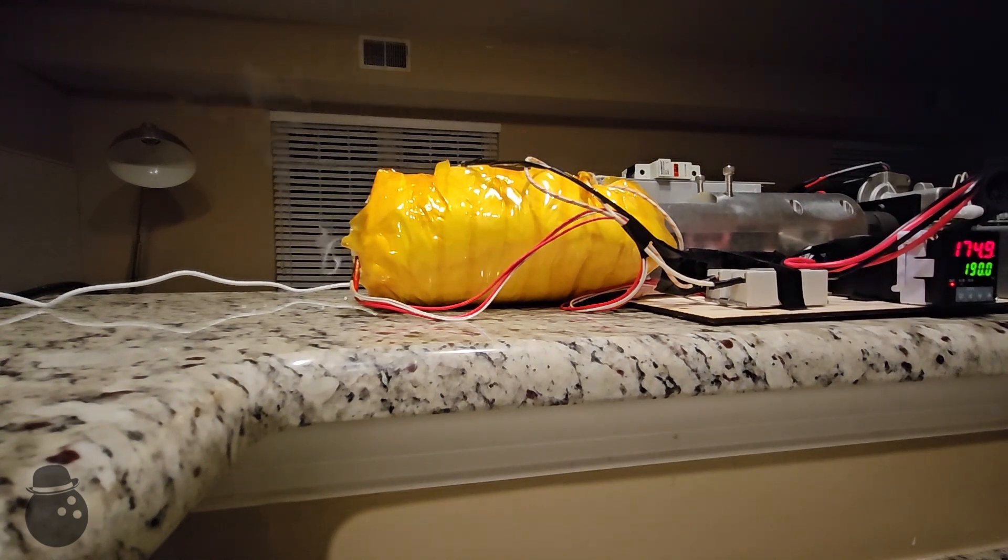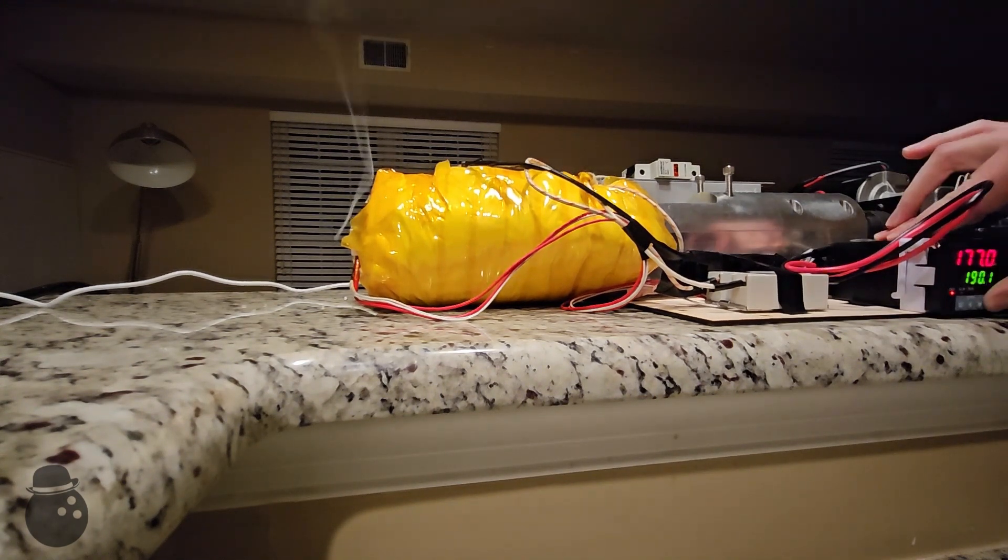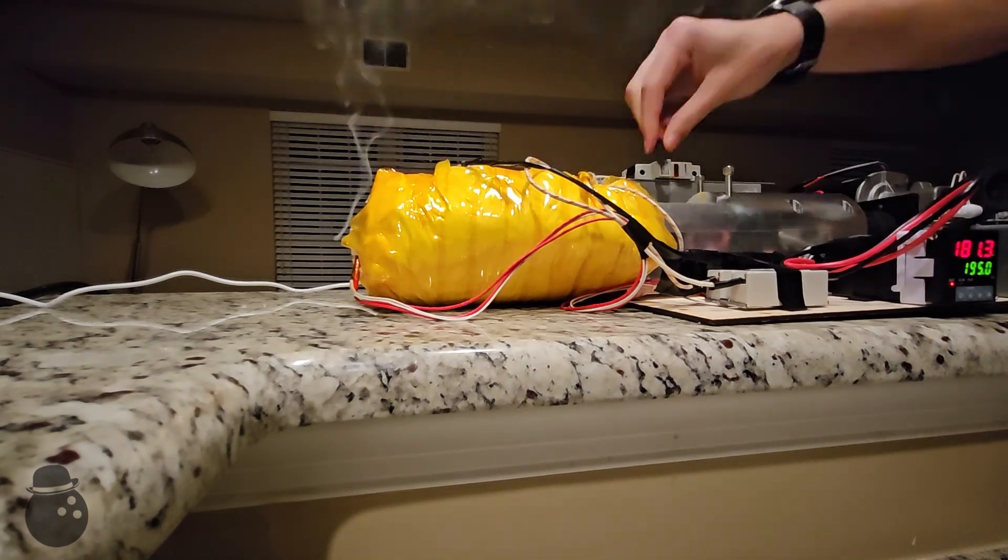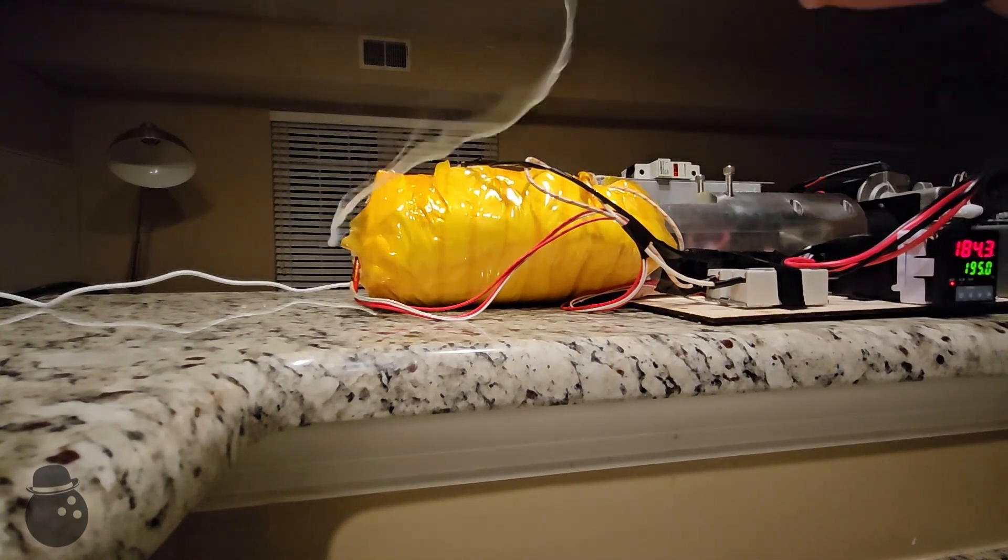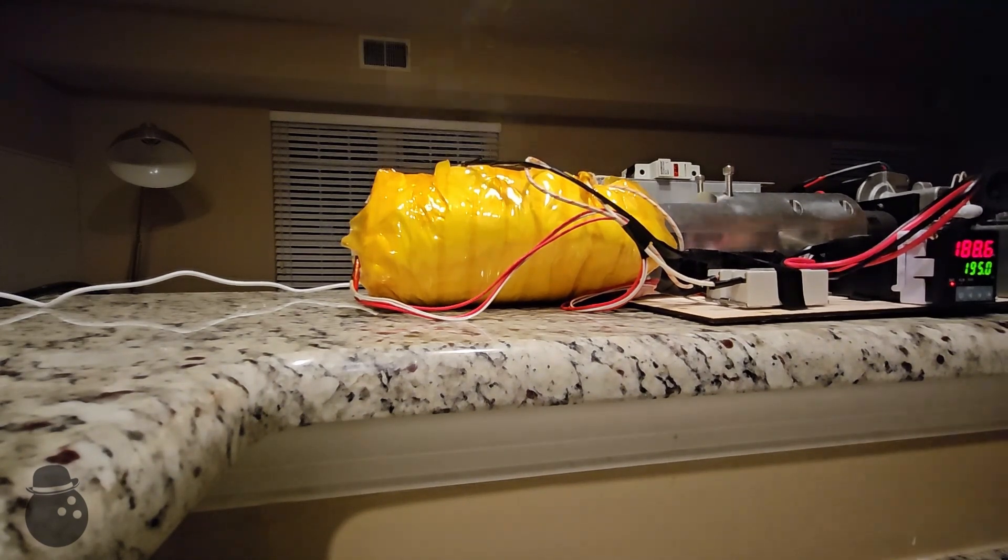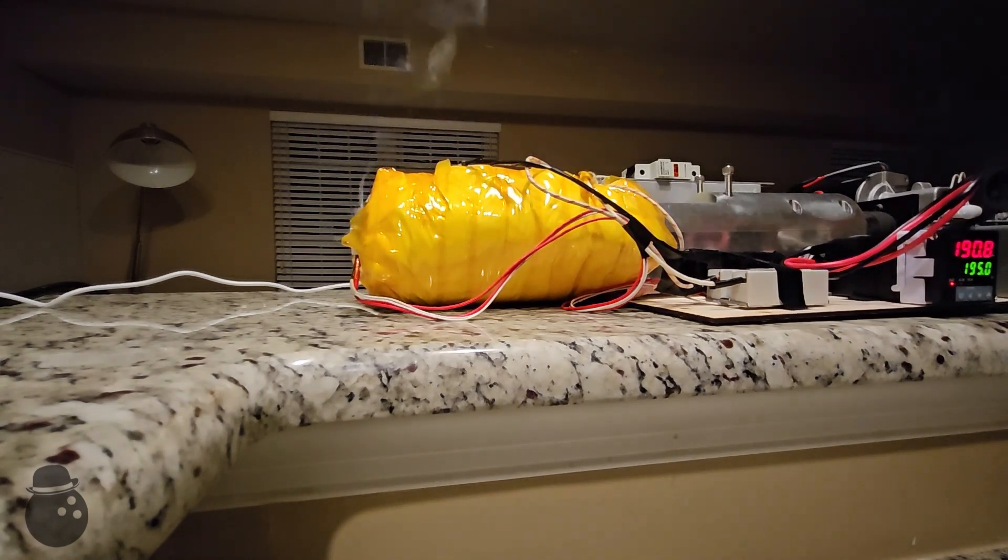Eventually, smoke appeared. It wasn't the electronics or a fire, so that only leaves that I wasn't properly melting the filament. I raised the temperature, which really only made it worse. And meanwhile, the motor began getting quite hot, trying to push plastic that just refused to move.